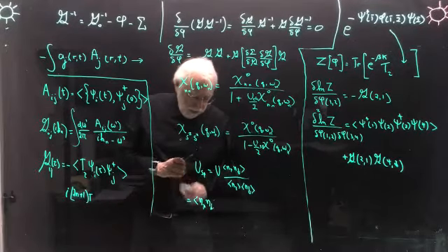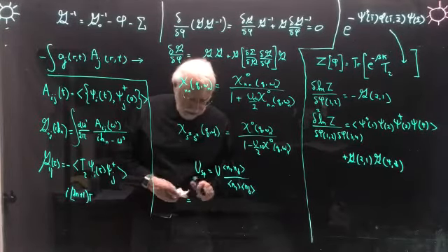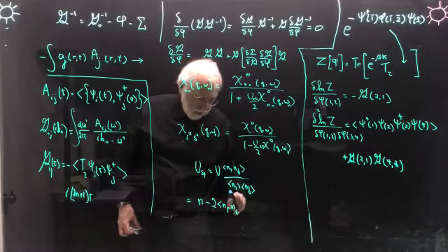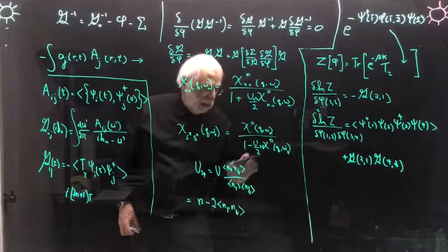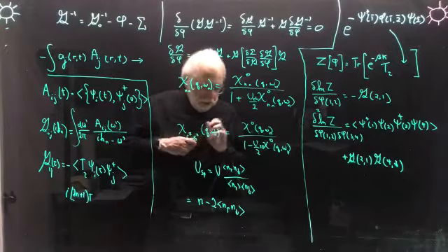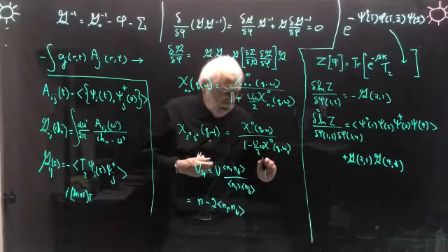I'm sorry. You get n up plus n down. So you get the total density n minus 2 n up and down. So if you substitute this here, you get a self-consistency equation for n up and down, and that's the 2-particle self-consistent approach, TPSC.